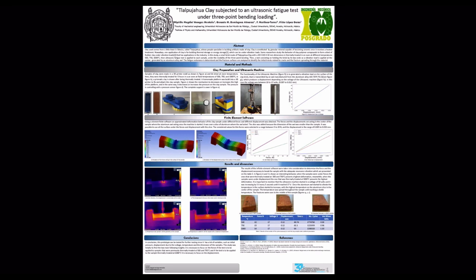The test consists of holding the brick by its two ends so a vibration load is applied at the center, generated by an aluminum alloy horn. The fatigue endurance is determined and the fracture surfaces are analyzed to identify the initial trends related to crack and fracture spreading through the material. The next section is clay preparation and the ultrasonic machine.